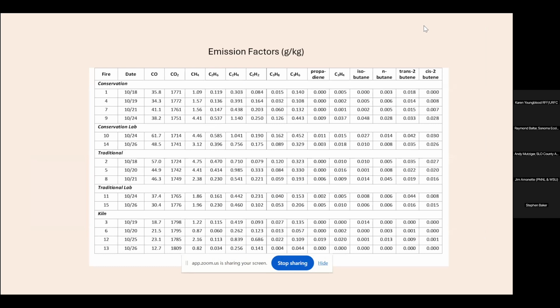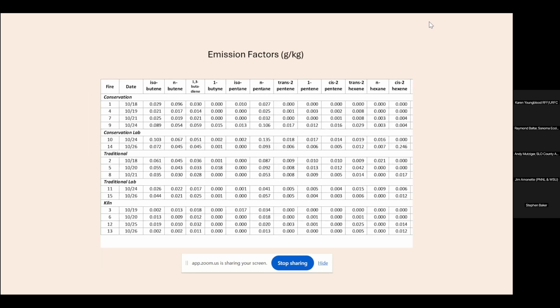Okay, so this is a table, similar to what we just saw, of the emission factors for other compounds, including the ones that we saw in the tables. Just to get some idea of what kind of levels we see for C3 and C4 compounds. They're generally, of course, much lower than the major compounds, but we did detect quite a few other emissions for C4s and C5s.